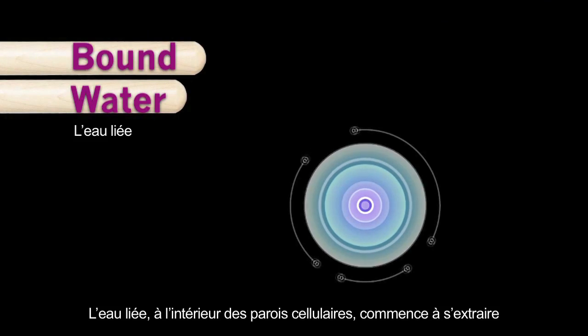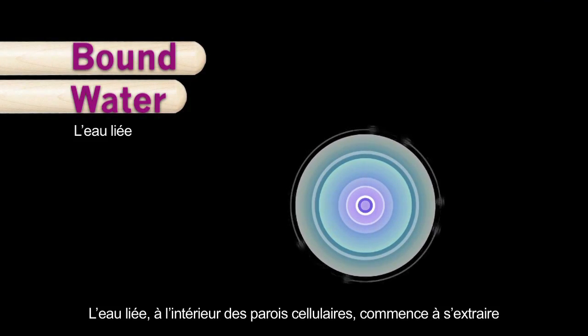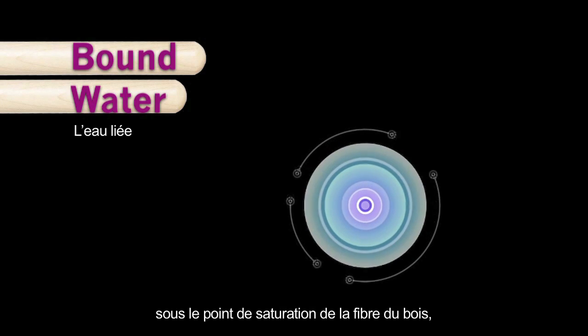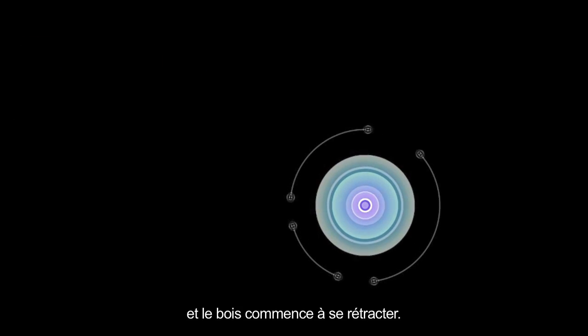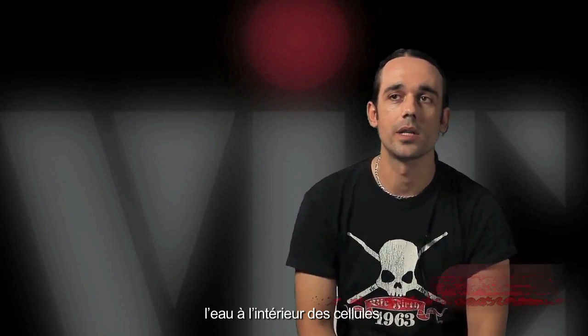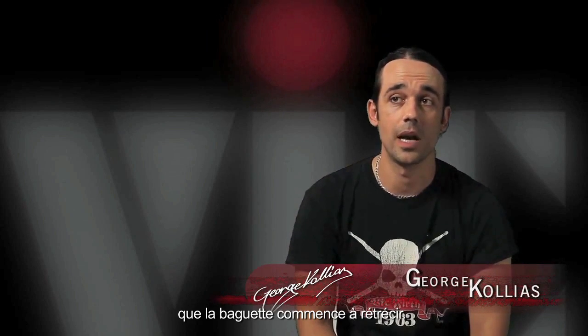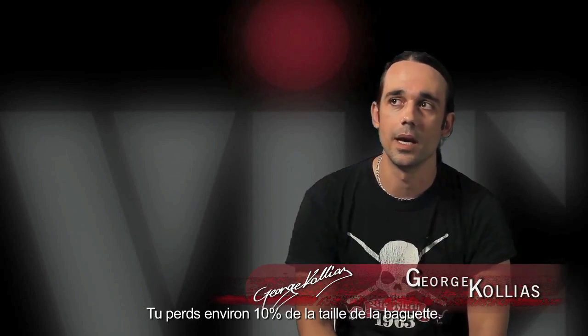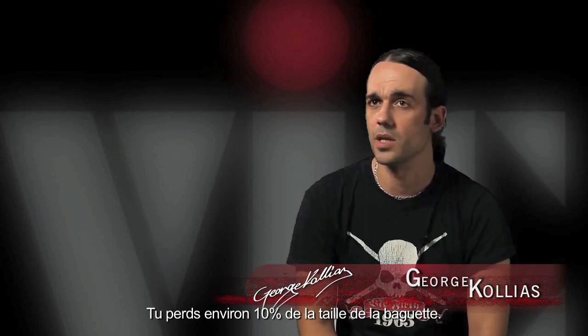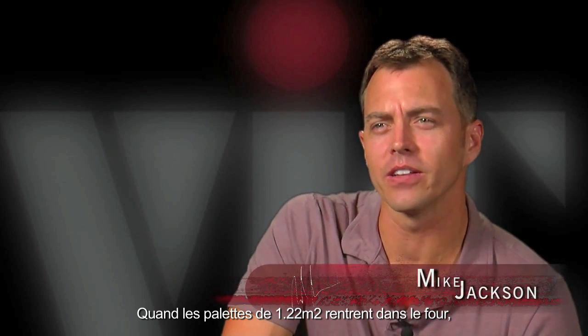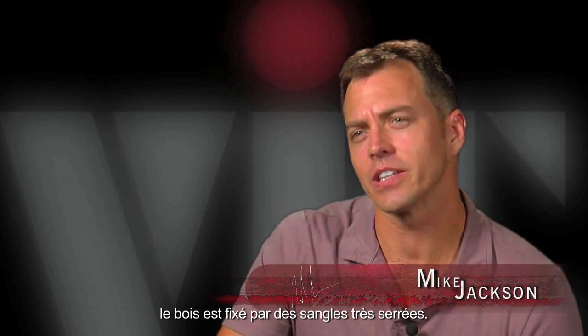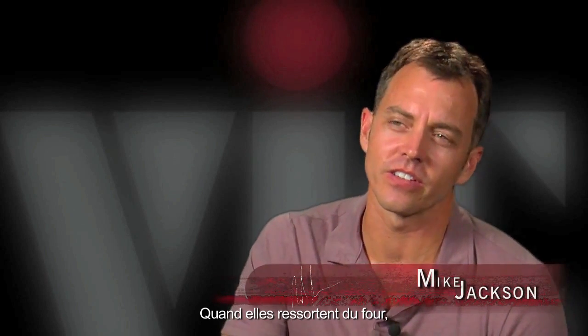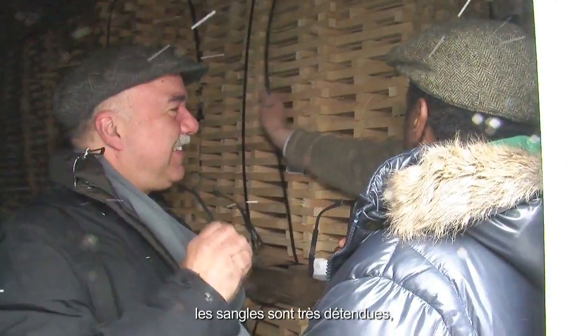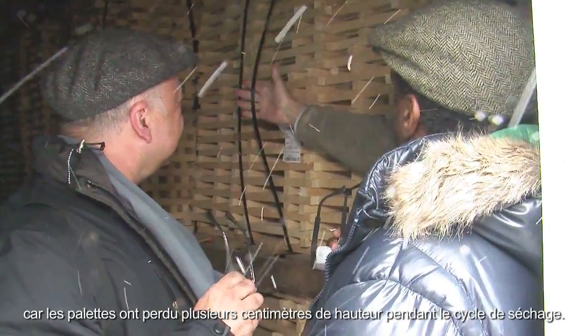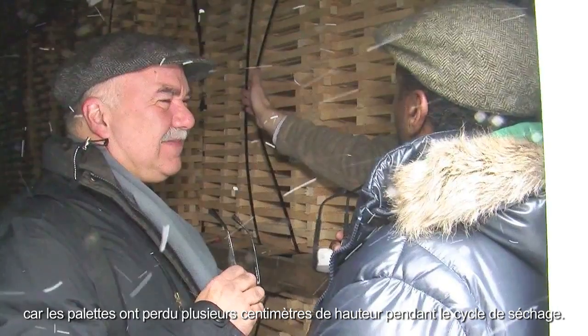The bound water found within the cell walls begins to extract under the fiber saturation point, and the wood begins to shrink. It's where you get to the bound water, the water inside the cells, and the stick actually begins to shrink. Then you lose somewhere about 10% of the size of the stick. When the 4x4 by 4 foot pallets enter the kiln, they are tightly bound. Upon exiting the kiln, the bands are loose due to the several inches of height lost during the kiln process.